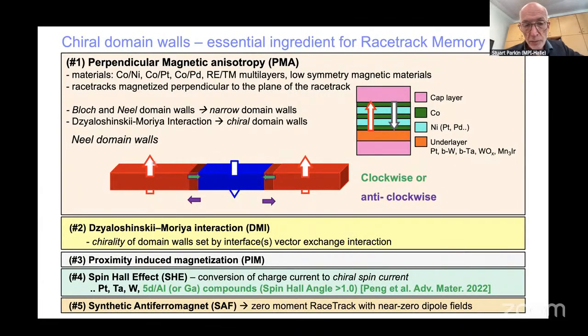And this means that when you go from up to down, then in the middle of the domain wall, shown by the green arrow, it points to the right. And when you go from down, the blue direction, to the up red direction, that green arrow points to the left. And this is chiral. So the chirality of these walls is formed by this interface Dzyaloshinskii-Moriya interaction.